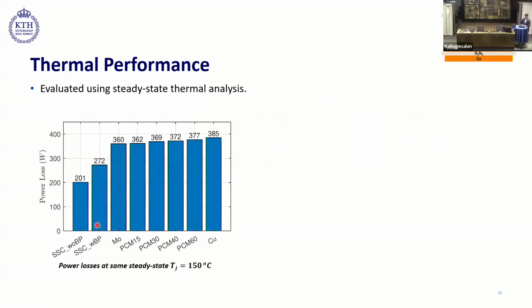Starting with the thermal performance of these packages, this was again evaluated at steady state. Again, here we are looking at the power loss that these packages were able to handle for the same junction temperature. So we see that double-sided cooled packages, which are represented by these bar plots, have higher power loss handling capability than single-sided cooled packages. Also, the power loss handling capability increased with increase in copper percentage in the spacer material.